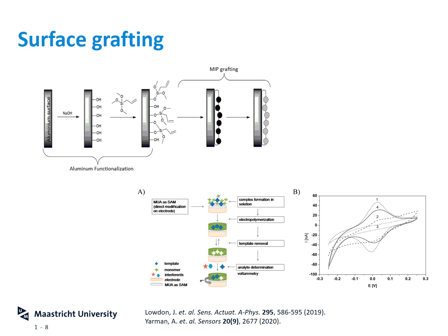Now, when you remove the target, in our case, we use the designer drugs molecule that's becoming very popular in the pre-corona rave scene, and we imprinted that and we extracted it and then did a rebinding experiment where we dissolved some of that powder in water and we were able to discriminate between that powder and a common adulterant. So you could use a sensor like that for doing a routine drugs test.